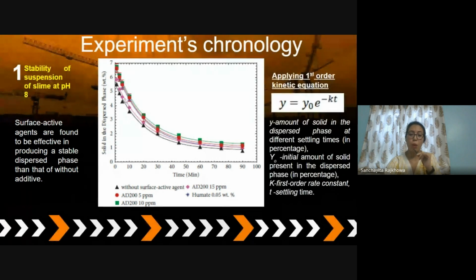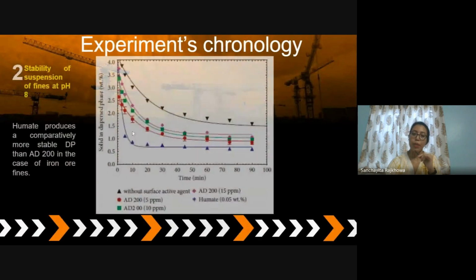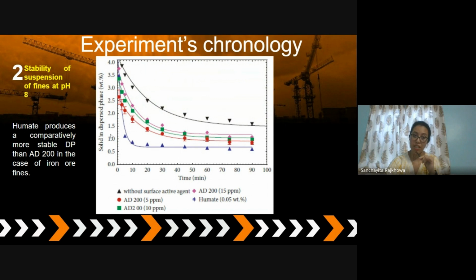Now, these points have been theoretically plotted using the first order kinetic equation, and it was well fitted with the theoretical equation. Now, a similar experiment has also been done with the fines, the suspension of the fines at that particular pH, and it has been studied. It was found that humate as a surfactant produces a more stable dispersed phase than that of AD200.